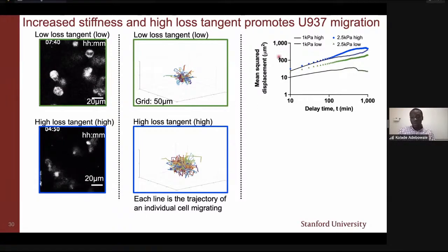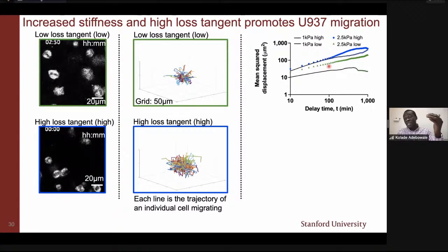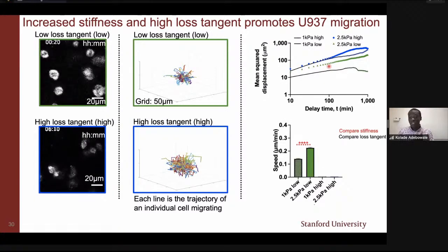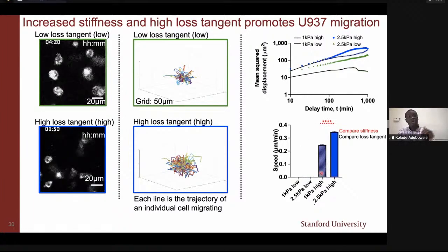And what this data on the top right shows is that if we either increase the stiffness of the material or the loss tangents, either of those independently increase the mean square displacement. And another way to see this is by looking at the cell migration speed. So for example, if we focus on just the low loss tangent material, if we increase the initial Young's modulus, we see an increase in cell migration speed. If we do the same experiment with the high loss tangent material, if we increase the loss tangents, we again see an increase in cell migration speed.